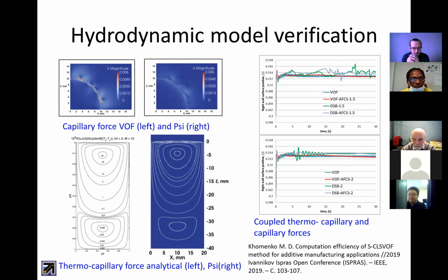But what I call the robust model is first of all a reliable model that starts from the verification of every part of that model, and that was done by us in the case of our model. We start from the hydrodynamic part. We used some analytical solutions to compare, and we show that our model is very good and can reduce the spurious currents that spoil the performance of the hydrodynamic models. That's why we can improve the performance of our model also.